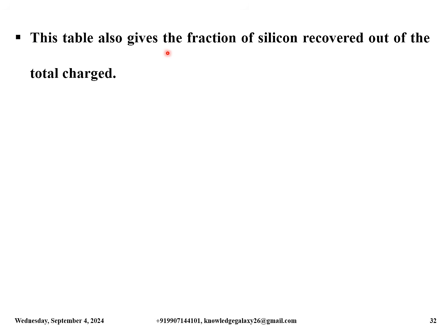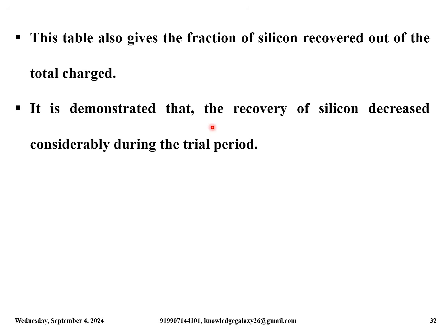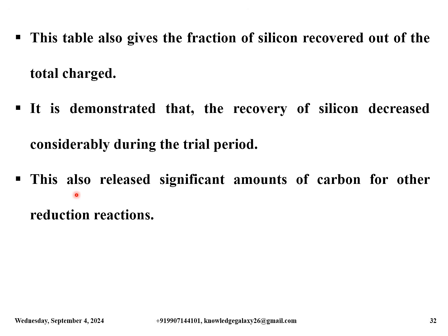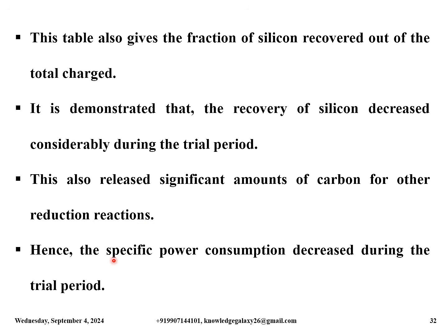So this table also gives the fraction of silicon recovered out of the total charge, the above table mentioned. It is demonstrated that the recovery of silicon decreased considerably during the trial period. This also released significant amounts of carbon for other reduction reactions. Hence, the specific power consumption decreased during the trial period.